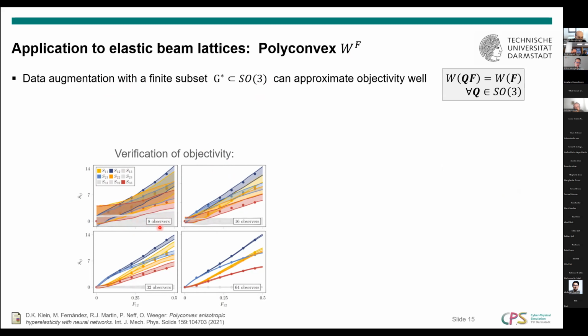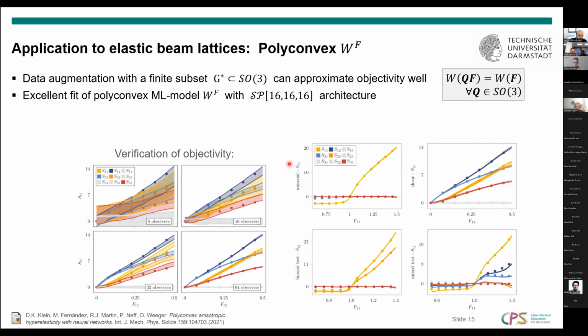So you see, if I use only 8 observers, I have a model that does not capture the objectivity at all. However, if I increase the number of observers for my data augmentation, now with 64, I can hardly distinguish the lines of the worst cases anymore and have a very good approximation of objectivity. And now if we fit this model to the data, we get an excellent agreement.